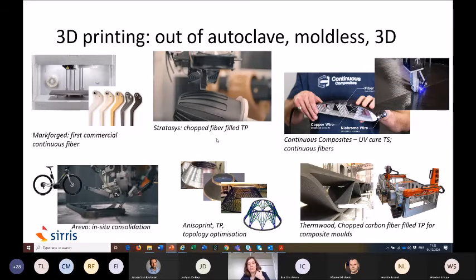Stratasys, they don't use a continuous fiber, but they use a chopped fiber. This is a very interesting company. They use a thermoset resin, and they embed the fiber with this resin, and then they UV cure. And the interesting thing is that they also can include wires and all kinds of sensors. Arevo, they make bikes with 3D printed composites. So they use a towpreg, which is impregnated, and they make all kinds of geometries with that. Very nice.